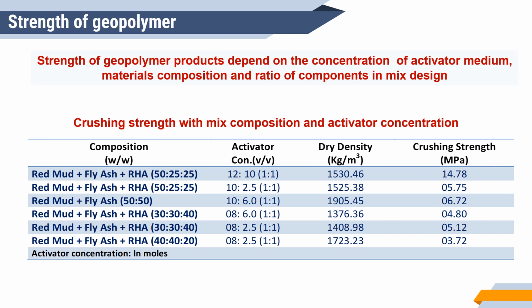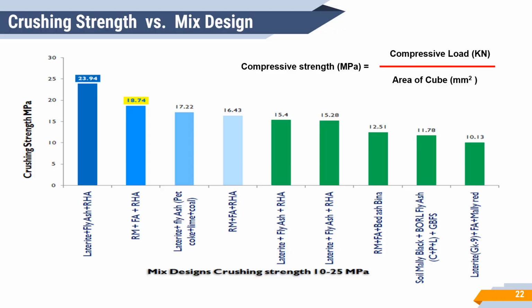In geopolymer matrix, the crushing strength is one of the important factors for using this material in building application. The strength of geopolymer products depends on the concentration of activator medium, material composition, and ratio of components in the mix design. Therefore, the utilization of the geopolymer product has to be decided for making a suitable alkali activator mix for dissolution of alumina and silica from the raw material. The crushing strength or compressive strength of some of the geopolymer matrix we have derived from aluminum industrial rejects in combination with other source material are shown here. Here we have achieved crushing strength ranging from 10 to 25 MPa, where the minimum required crushing strength is 3.5 MPa for its use as building material.